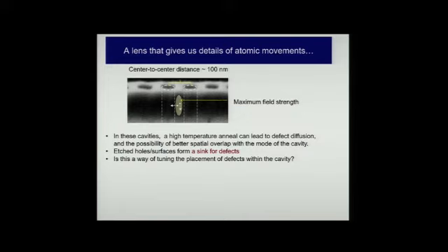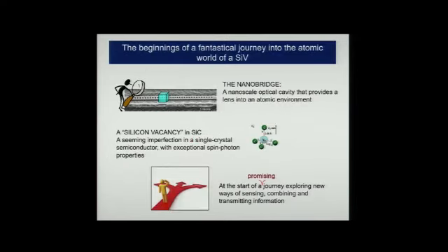And what's interesting is, you know, this distance is 100 nanometers. It's not a very high distance. So actually, the distance between a defect and the nearest surface is probably half of 100 nanometers. So we can imagine during this annealing process, we are maybe annihilating defects that are interacting with the surface. We are thinning the intensity of defects. And maybe occasionally, we are nudging a defect into exactly the right position in the cavity. There's a lot for us to understand here, and those simulations and experiments are underway. So this is sort of the journey.